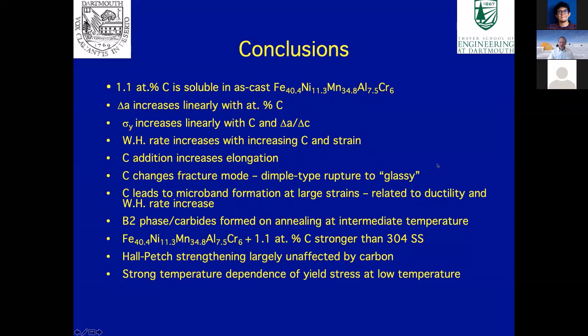And the carbon leads to this microband formation of large strains, which we think is the reason we get very good ductility and high work hardening rate. If we do thermomechanical processing or simply just annealing, we get second phase ordered body centered cubic particles forming, or carbides at hard temp in the material.